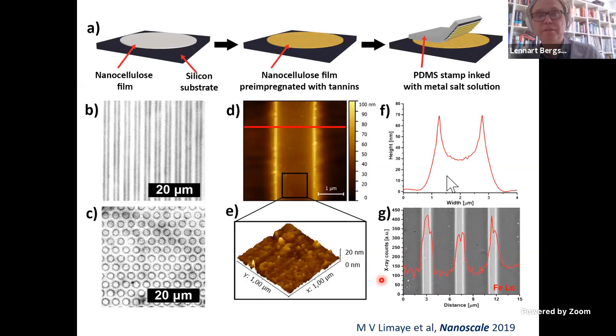We have utilized this in a simplified patterning process, where we pattern nanocellulose films using this kind of soft lithography approach, using both stripe patterns and these kinds of dots.